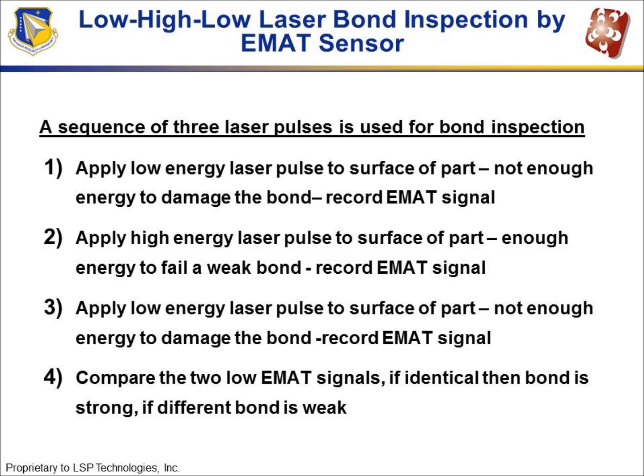The magnetic field lines that are produced by the inspection head run parallel to the surface of the tape. The laser beam comes in, and as a result of the shock wave that is produced through the composite, that surface starts to move. As the conductive pattern moves through the magnetic field, an electrical current is set up in the path. That electrical current is sensed by the EMAT. So it is able to detect the surface velocity, the surface motion, just like a VISAR, and determine exactly what type of variation the bond line is going through as a result of the interrogation that LBI is doing.